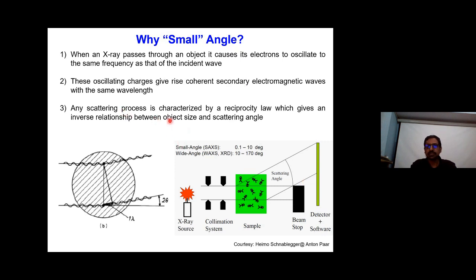Now, any scattering process is characterized by a reciprocal law. If you remember Bragg's law, it states n lambda is equal to 2d sin theta, right? So theta is inversely proportional to d. What I'm trying to say is that if your scattered radiation is at low angle, the d will be high. d is the size window, or the dimension of the system, which you are looking at. There can be two types of angles: small angle, which is between 0.1 to 10 degrees, or wide angle, which is 10 to 170 degrees.